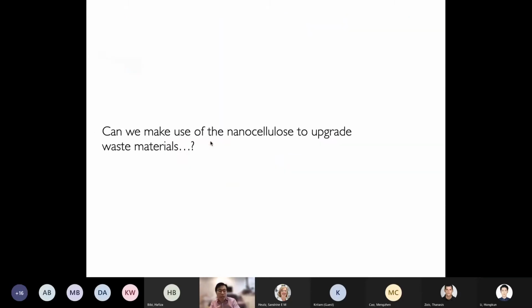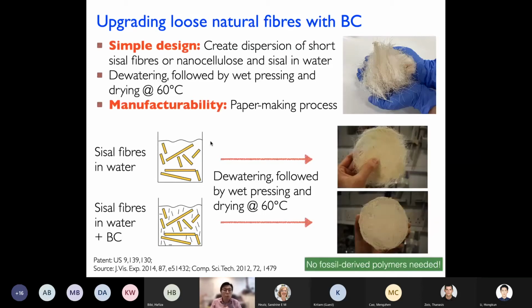Now, we talked about nanopaper as a useful material structure, but what else can we do with nanocellulose, particularly utilizing the hornification effect to upgrade properties of materials, particularly waste materials? We did this with natural fibers, so you have loose natural fibers to start off with. So typically you would then compound that with a polymer to create a natural fiber reinforced renewable composite, for example. But what we did here was to use bacterial cellulose once again as the binder to bind these fibers together.